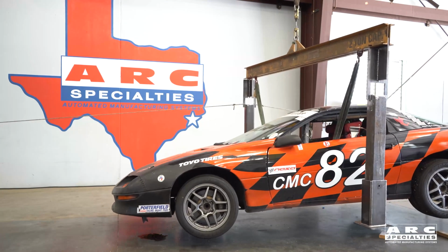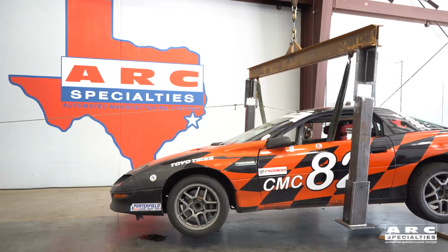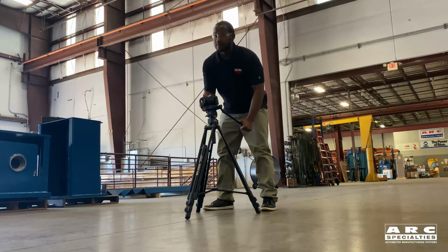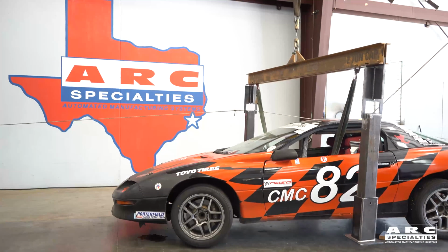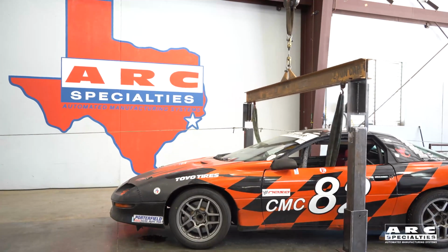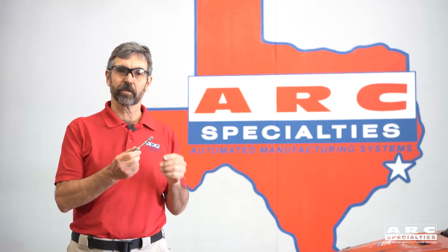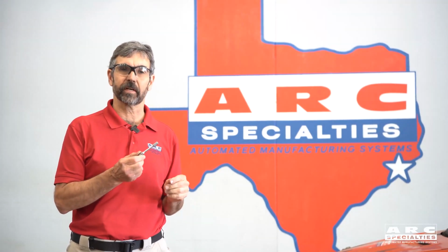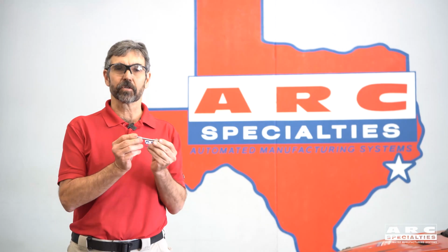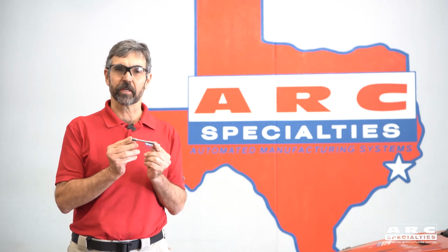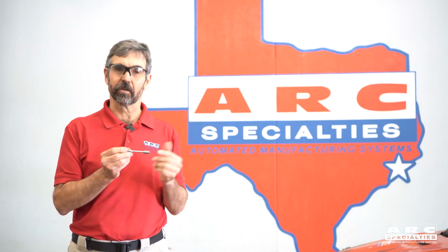Indeed it did. To show our confidence, we've asked Johnny, our photographer, to stand underneath the car. Well, maybe not. I consider that a successful test. Additive manufacturing tensile specimen, 163,000 PSI yield strength, 171,000 tensile strength, or in units of race car, greater than 1.